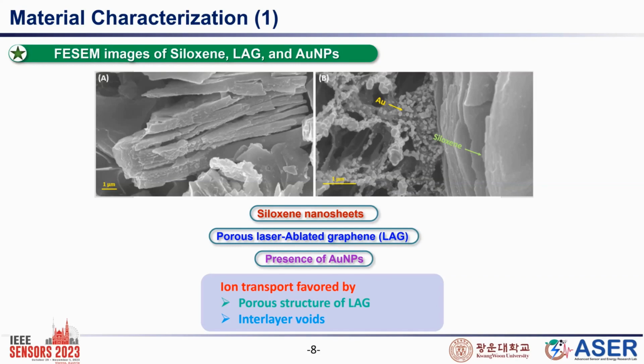And the presence of gold nanoparticles favors the ion to electron transition, as well as gives high surface area. So this combination actually works well. So ion transport is favored by the porous structure of the LAG, as already mentioned, and also the interlayer voids of the 2D-Siloxene. So 2D-Siloxene materials have some kinds of interlayer voids, which facilitate the ion to electron transduction.